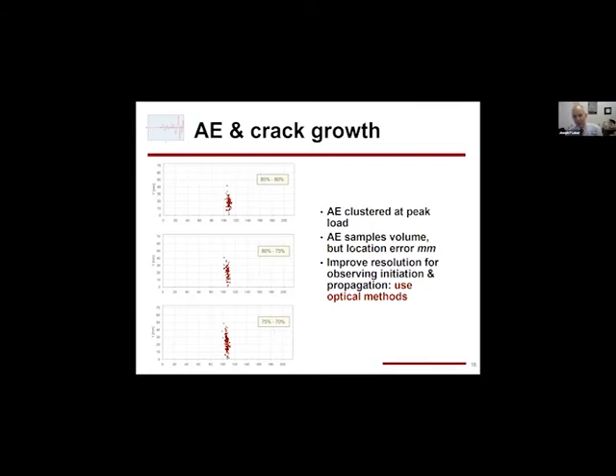So I would argue that AE may be one of the most effective ways of monitoring fracture, including propagation. It has the advantage of sampling the entire volume. A disadvantage is, of course, there's location error. So if we want to determine a crack length of 10 millimeters and we have an error of plus minus 2 millimeters, that may not be of a fine enough resolution. So what to do? Well, in a laboratory setting, we can use optical methods.